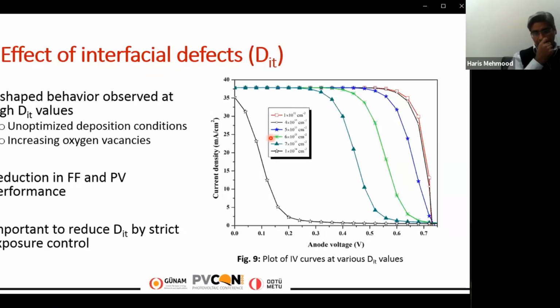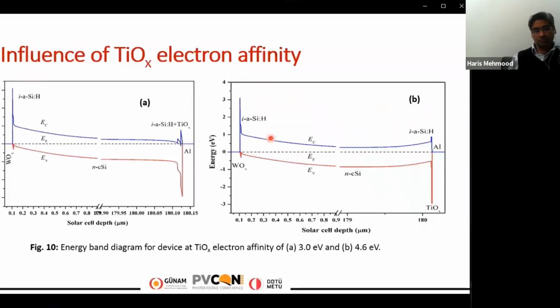So by decreasing the oxygen vacancies, the Fermi level will be pulled away from the conduction band minimum, so the work function value will increase. So it is very important to reduce the interfacial defects by strict exposure control. Similarly, we have also studied the influence of the titanium dioxide electron affinity on the band bending.